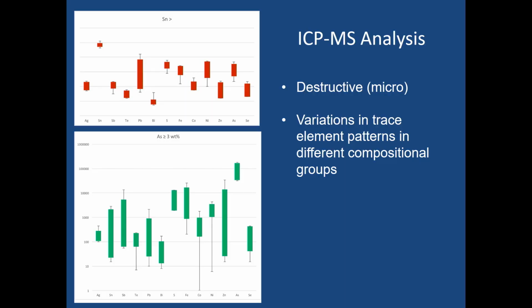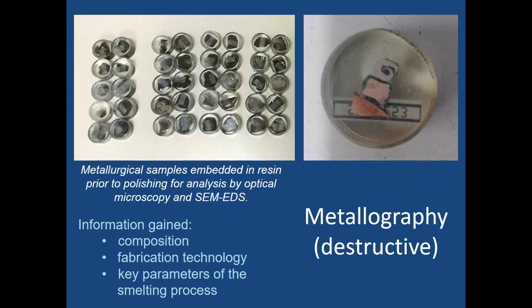However, if we want to draw more out of those materials, we usually need to use a different range of approaches. We also have done trace element analyses using ICP-MS, and they tell us about different trace element patterns between the tin bronzes, between the different copper alloys at the site, which tell us about different compositional groups and potentially different sources for this material. But given that so much of the material is so abundant at the site and so much of the slag is not going to be displayed in the museum at any point, we also undertake substantial amounts of more destructive analyses on some of this material.